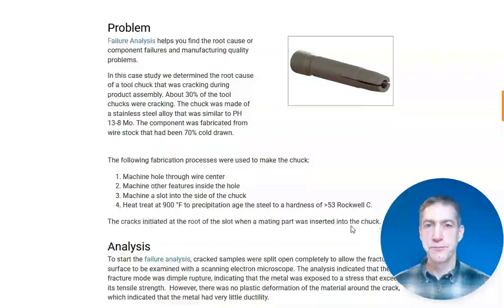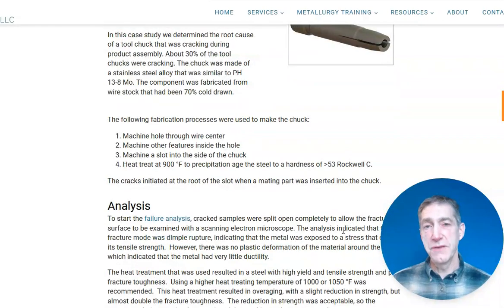and this machined slot was a stress concentration. So we recommended using a different heat treatment, heat treating at a higher temperature that resulted in slightly lower strength but better fracture toughness, to improve the resistance to forming a crack after the part was heat treated. That indeed worked. Even though there was lower strength after the heat treatment, the improved fracture toughness was okay, and the lower strength was also okay. And the result was that there was no longer any cracking of the component after the heat treatment.